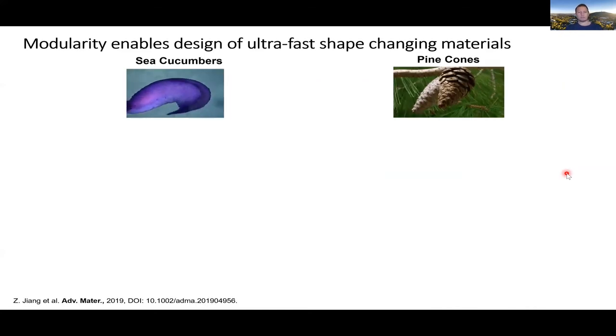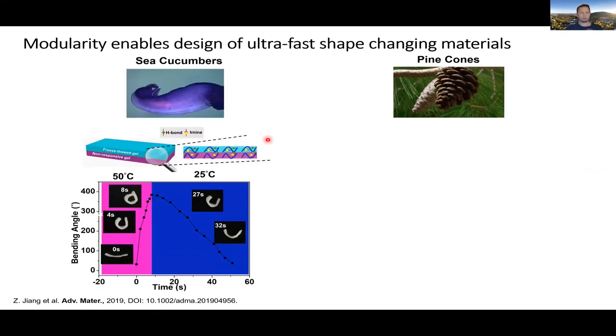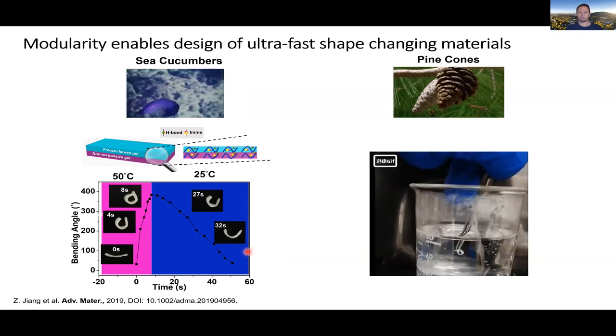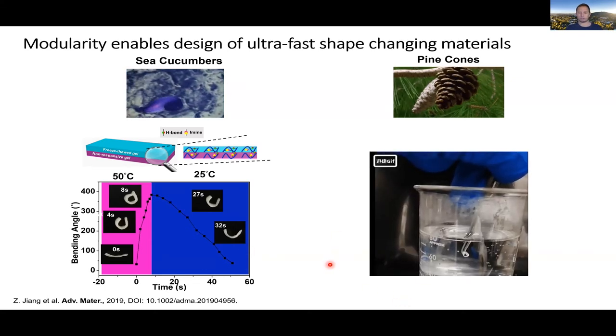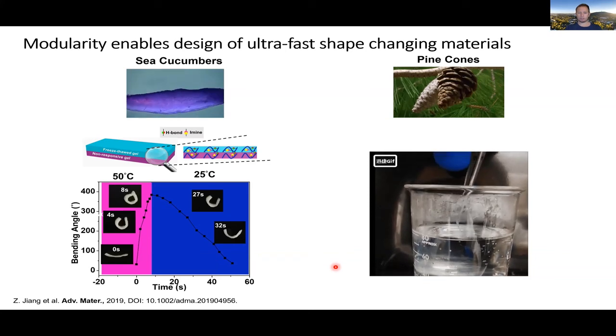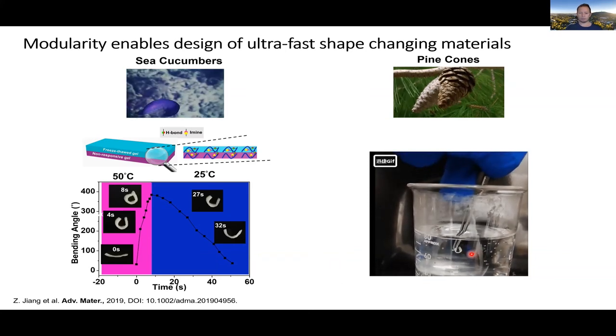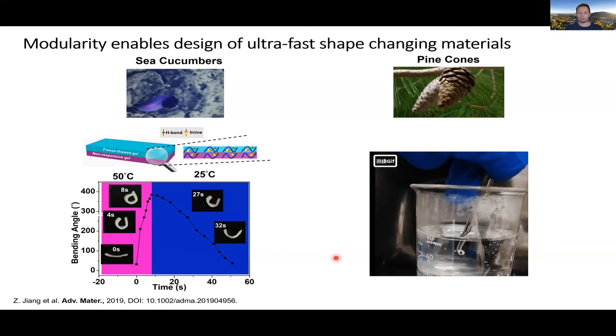This is this idea of changing shape with some sort of stimulus. These materials, we can design in a bilayer structure, where one layer is non-responsive and the top layer is responsive, and we can make these temperature responsive. So at 50 degrees, this will curl up, change shape, and then it will reverse back at 25 degrees. Here is a little video of us doing that. This is Jen holding this object, and it will curl up at 50 degrees almost instantly, within seconds.